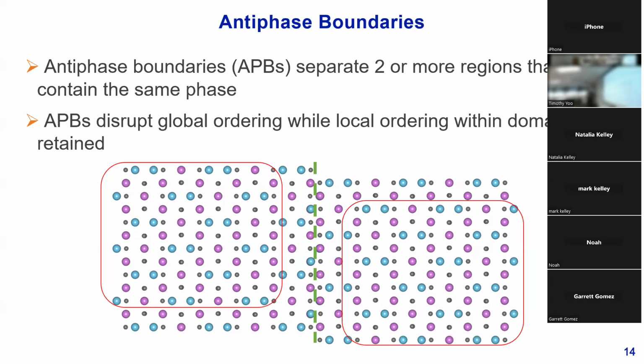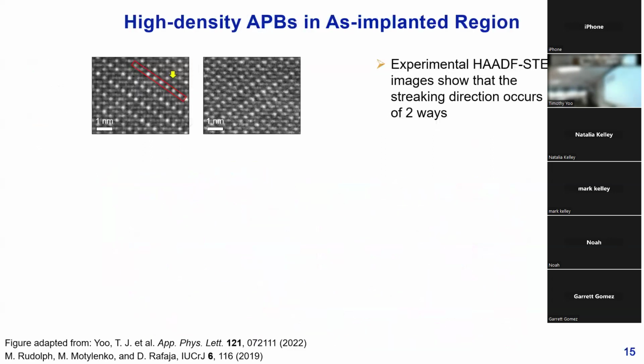So what are anti-phase boundaries? Well, if we assume that this anti-phase boundary is represented by this dashed green line here, what they do is they'll end up disrupting the entire global ordering of your system, while typically the local domains, aside from the boundaries, like the ones in these red boxes here, are going to be well retained. So while the local ordering is okay, the global ordering is going to be disrupted. And the anti-phase boundaries are usually going to be defined by some type of lattice shift in 3 dimensions.